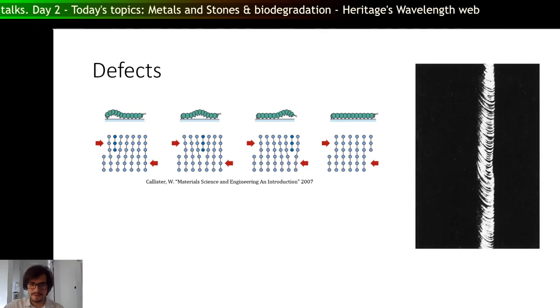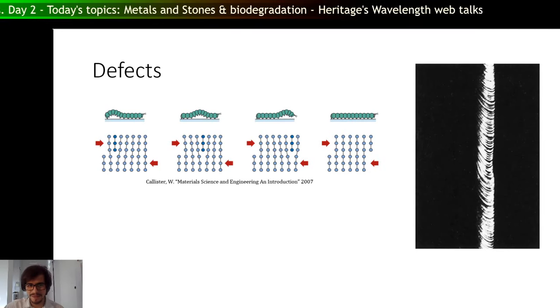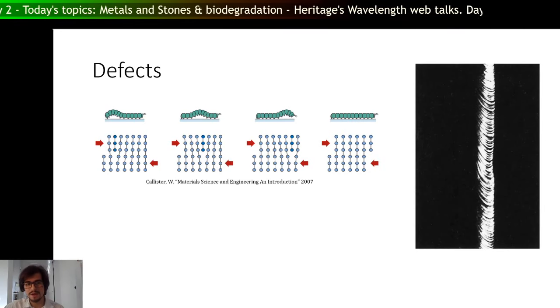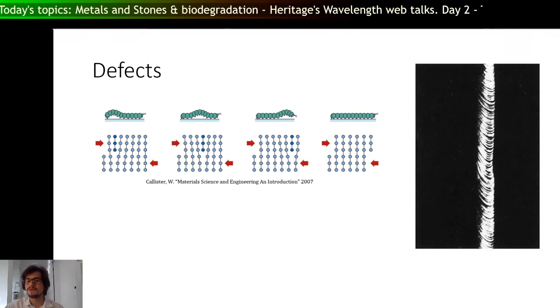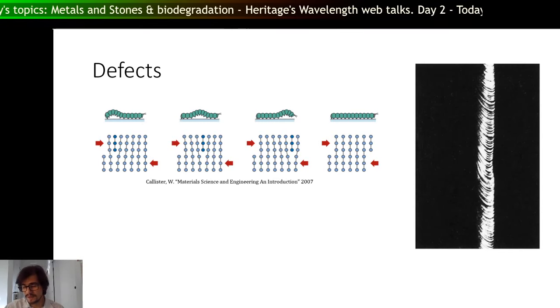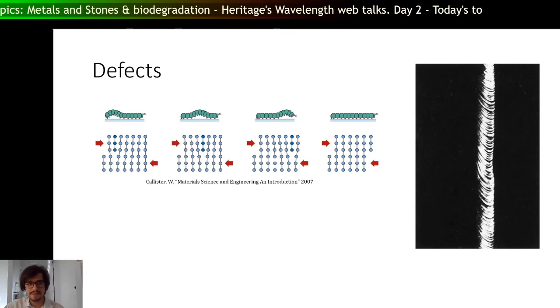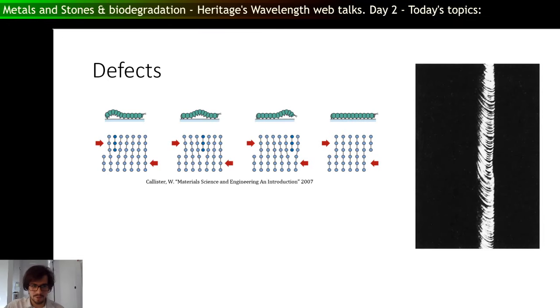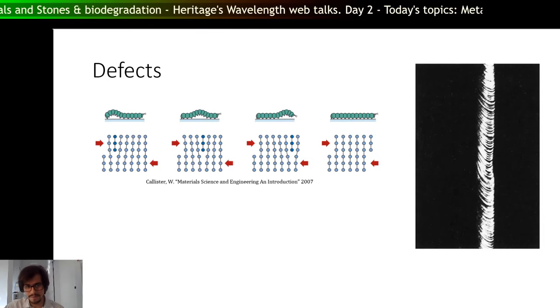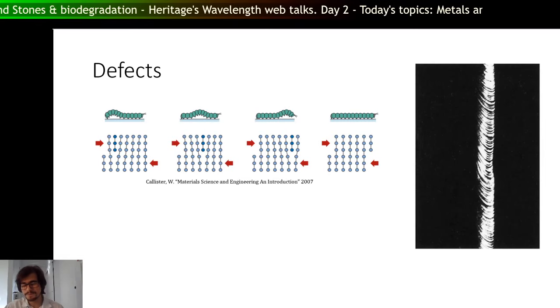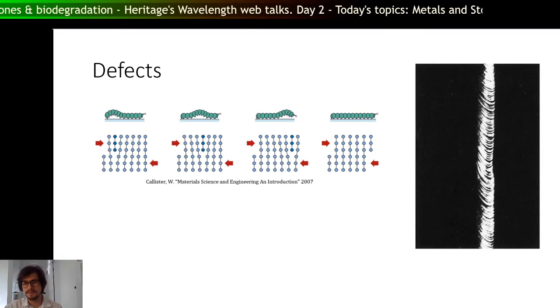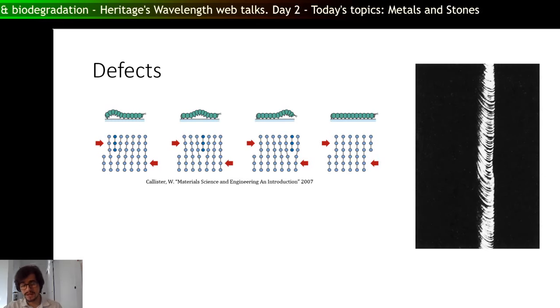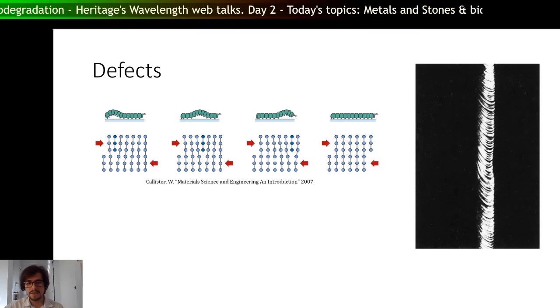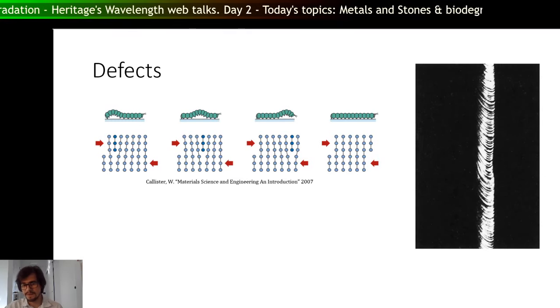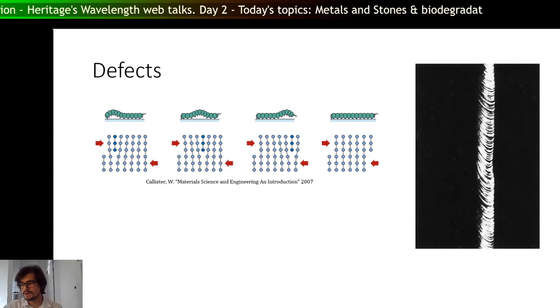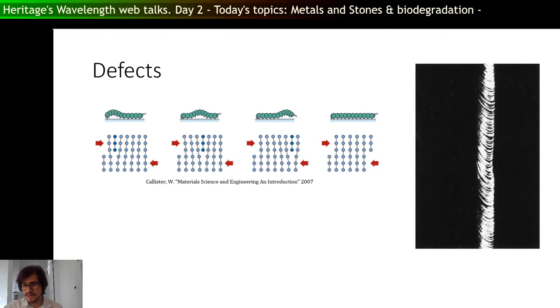So this cute little image here with the caterpillar shows you the motion of defects inside the metal crystalline grid. See this line that ends abruptly in the middle of the crystalline grid, this one with darker balls. When you apply stress to the metal, this is called a dislocation, just for a fact. It will move on inside the crystalline grid, so it absorbs part of the energy that was applied to the metal and moves on.